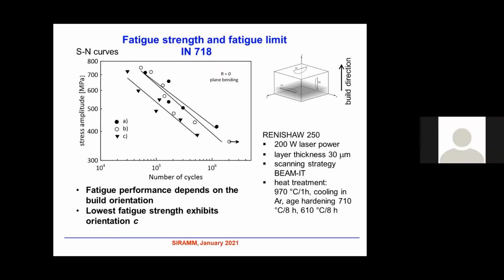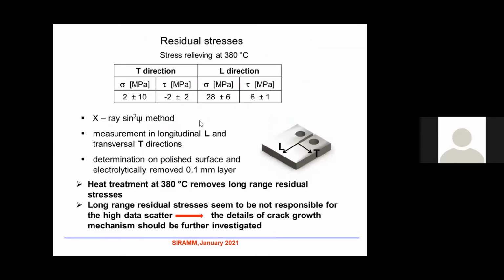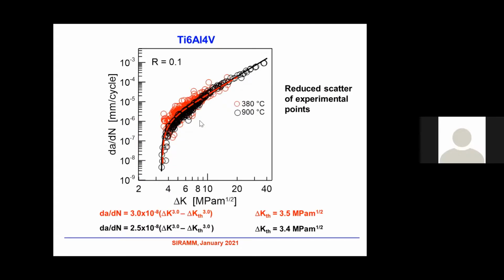And once the crack is initiated, when the crack is growing, then there is no more influence of the microstructure in long crack propagation. It depends on material and on the structure, definitely. I showed you only two cases here: Inconel and titanium alloy. And I've seen that in the Paris domain, there is influence of microstructure only, you showed us, in case of Inconel.